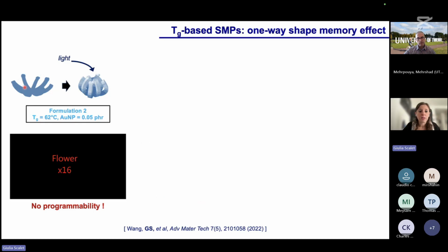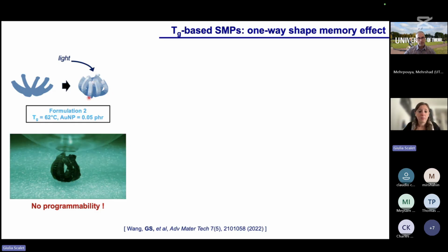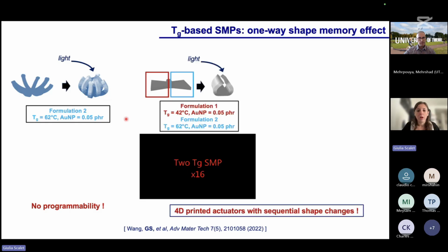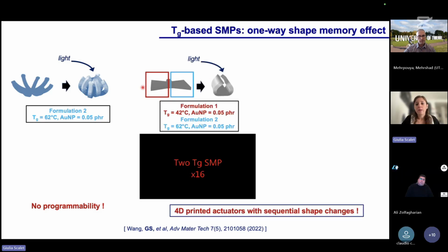You print this structure, you fix this deformed temporary shape, and upon light irradiation, in this case, because the material is composed of gold nanoparticles, you can obtain through indirect heating the initial shape. So this is a very simple example, but it is not programmable. This is why we have been working on programmability by using two materials.